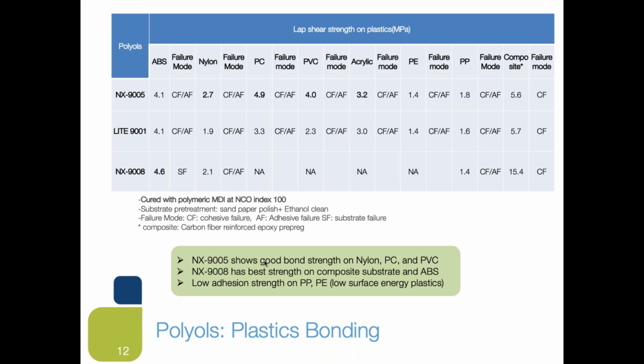Polyurethane adhesive and coatings have been used for protecting and adhering plastics for quite a long time. A main reason is that, unlike epoxy, polyurethane is quite flexible and soft like a plastic in general, so it can provide excellent adhesion and performance. So what we have done here, we selected key plastics like ABS, nylon, PC, PVC, acrylic, and PE and PP. We also included a composite, carbon fiber reinforced epoxy prepreg composite, to test the adhesion performance of selected polyols.